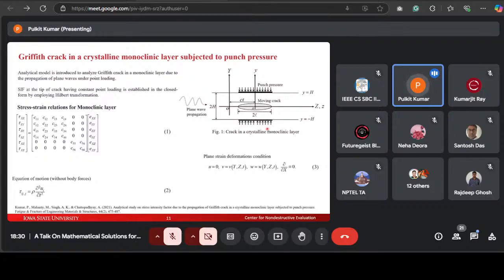Now a coordinate system OXYZ is chosen in such a way that the layer is defined by the whole plane in x and z, and the y-axis lies between minus H and plus H, and the crack is defined by mod z less than or equal to L at y equals 0. It is assumed that the crack is moving along with the parallel punch pressure acting on the bounding surface of the layer with a uniform speed c along the z-axis.